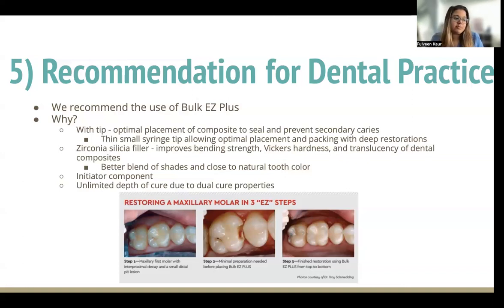With the tip, Bulk EZ Plus is able to combine the placement of a flowable composite along with the properties of a packable. This allows deep placement as it cures, and its in-depth curing prevents breakage. The addition of the zirconia filler improves bending strength, Vickers hardness, and the translucency of the dental composites. This allows us to create better, more natural restorations while also taking into account great strain and usage, again, during mastication and occlusion. Because of this, we recommend the usage of Bulk EZ Plus at our practice and believe that both patients and the providers will benefit greatly.